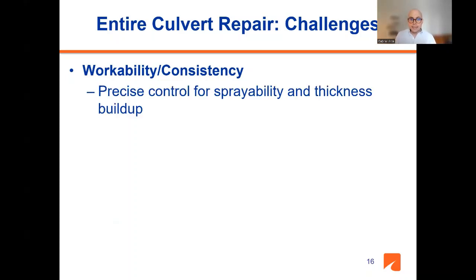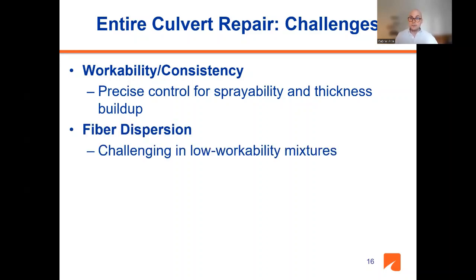So one of the challenges is having to change the workability of this ECC. First, to be able to successfully be sprayed, you need sufficient workability, but then it has to have the rheological properties to produce that thickness buildup as you're spraying, especially when you spray overhead. Then fiber dispersion is challenging because these are very low workability mixtures, so it's very difficult to disperse the ECC fibers in these mixtures.